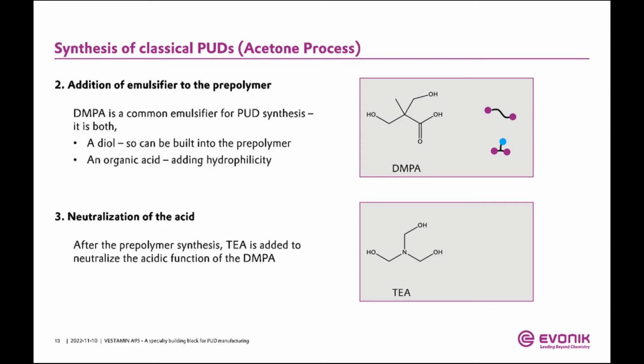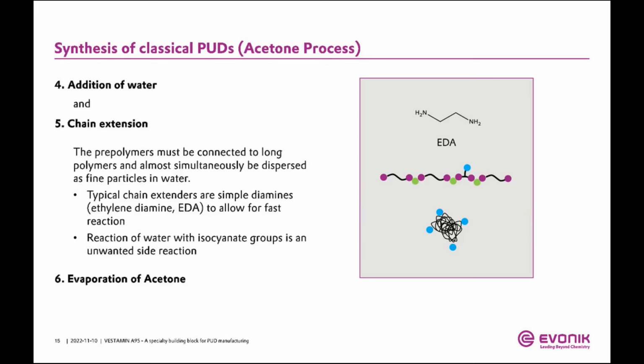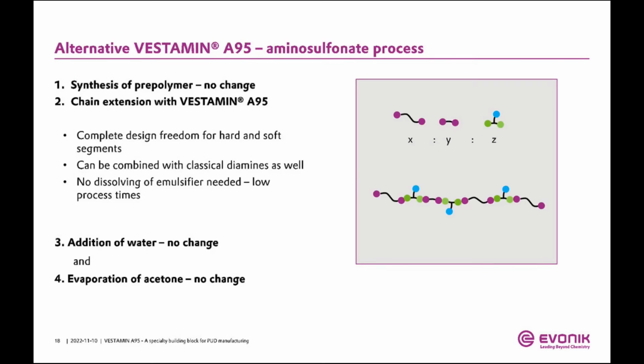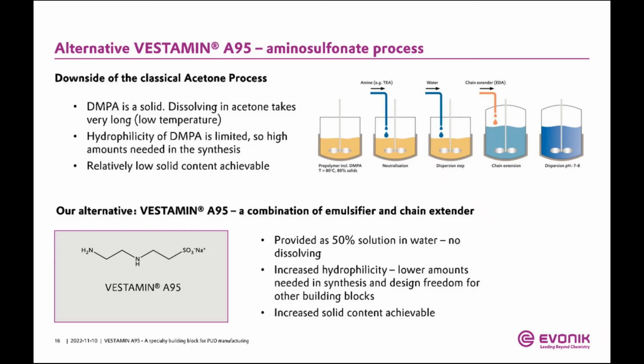The effect is that in classical DMPA-based PUDs, often the TEA, the amine, is later evaporated from the PUD and released. Then you go back to the DMPA, so it is back to this original acid state and it is less hydrophilic again. Less hydrophilic after the application is an advantage, because the water is not affecting the product so much. In the A95 case, we always start with the salt, and the salt stays in the system, so the hydrophilicity stays. And this is the reason why we have less water stability.